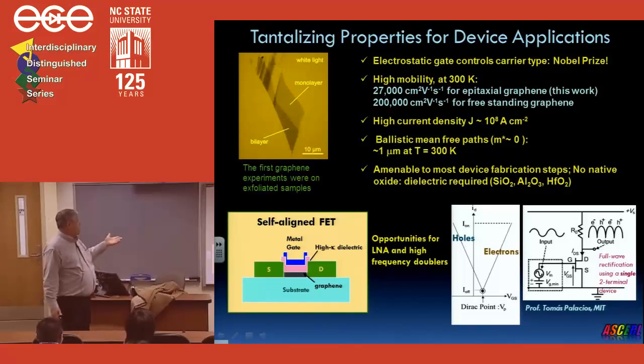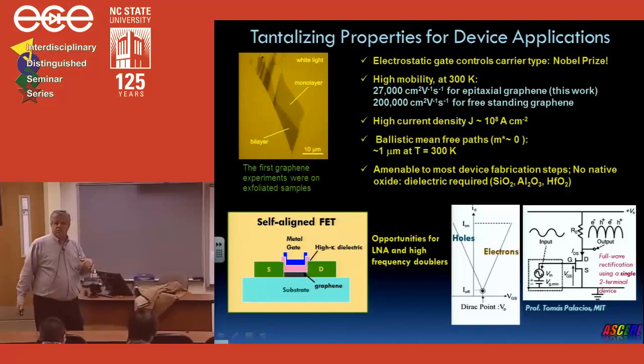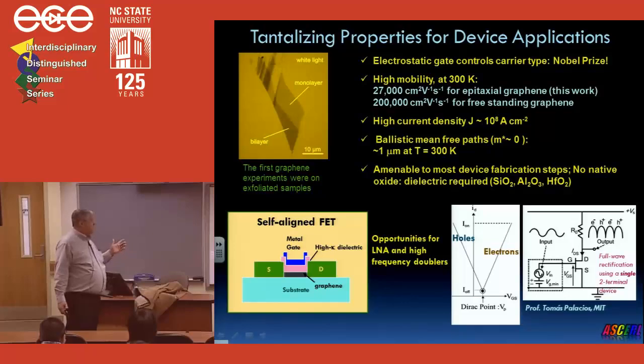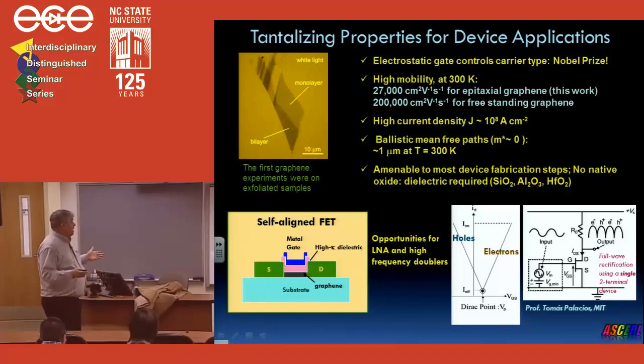And it's also amenable to all the standard processing steps for silicon processing. And that makes it very attractive. About the only thing it's missing is it doesn't have a native oxide, because if you try to oxidize graphene, it evaporates. So you have to put your own dielectric down, and that has its own challenges, which I won't be touching upon today. There's other potential application space.